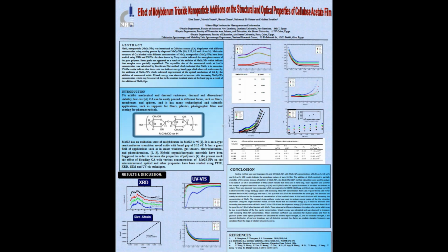Tauc equation was used for the analysis of optical transition occurring in cellulose acetate and cellulose acetate blended with different concentrations of nanoparticles. The optical transitions in the films are indirect in nature. Two energy gaps were observed, corresponding to the HOMO-LUMO gap and the onset gap. A gradual decrease in the energy band gap was observed, which was for the HOMO-LUMO band gap